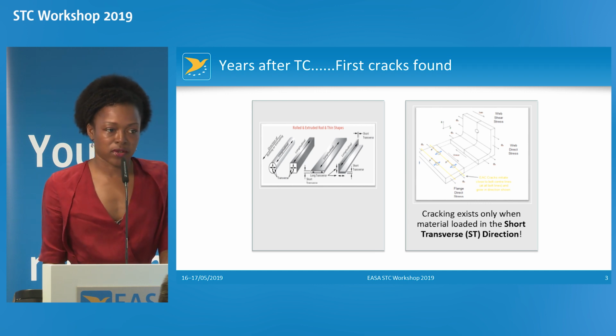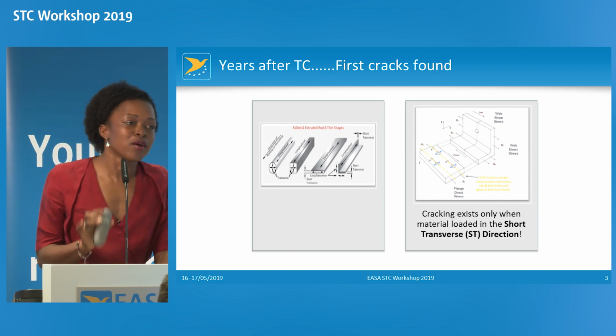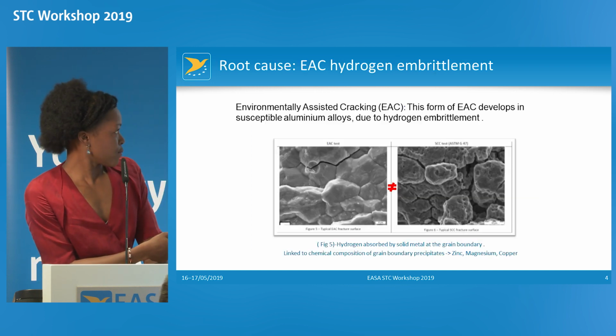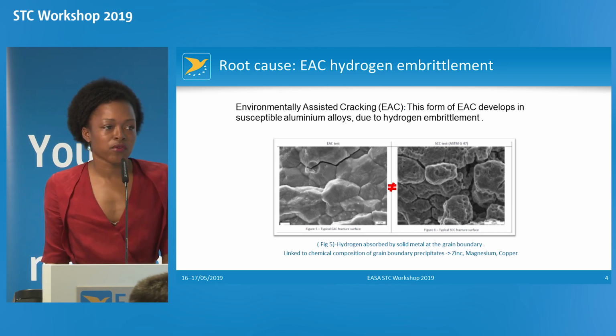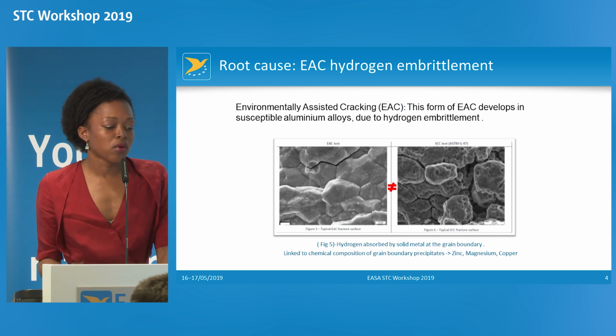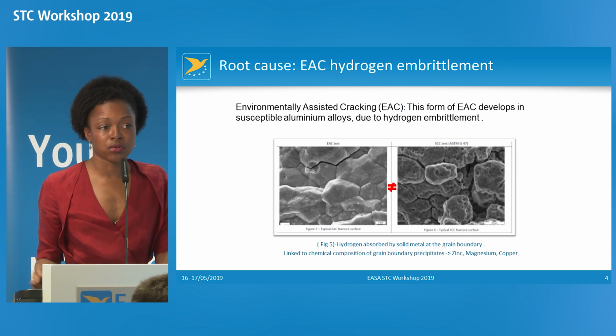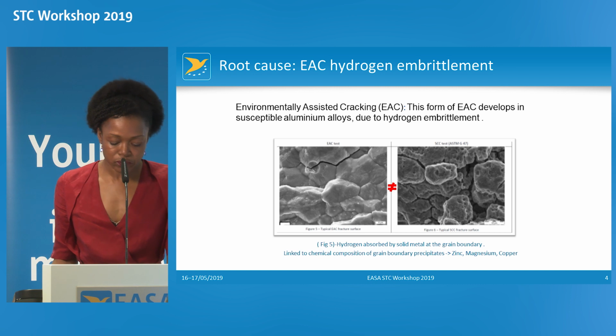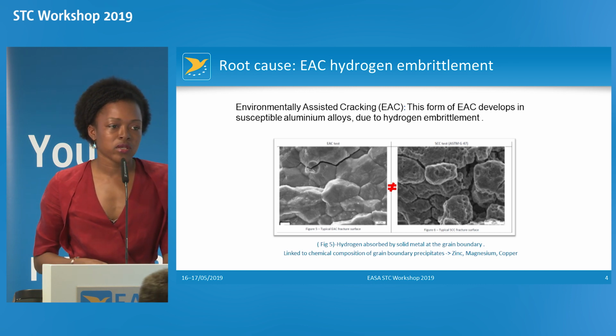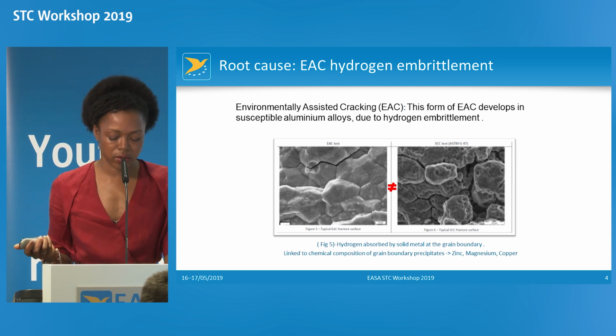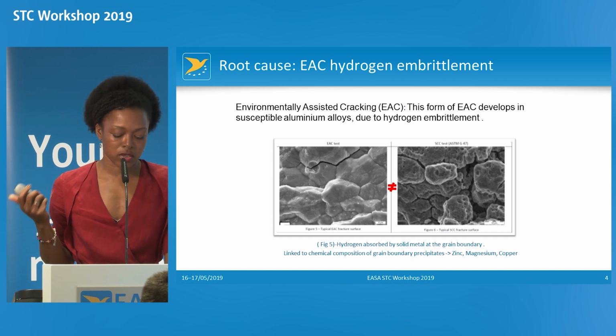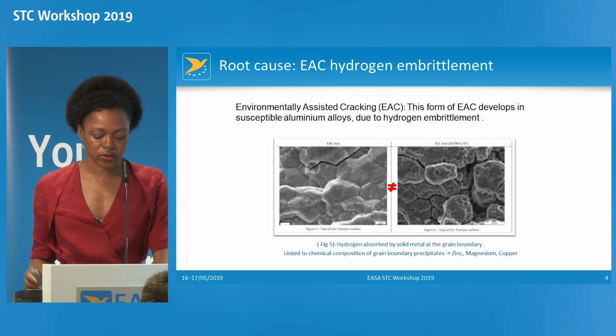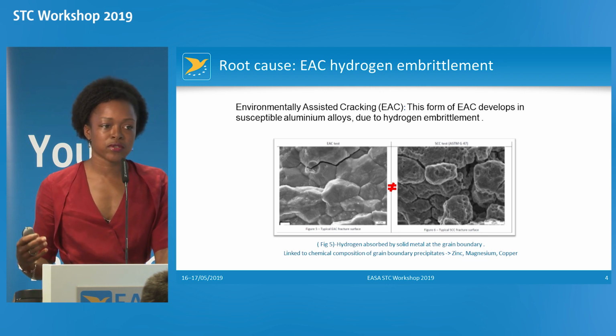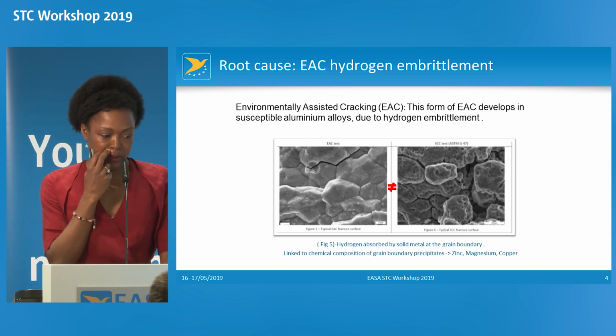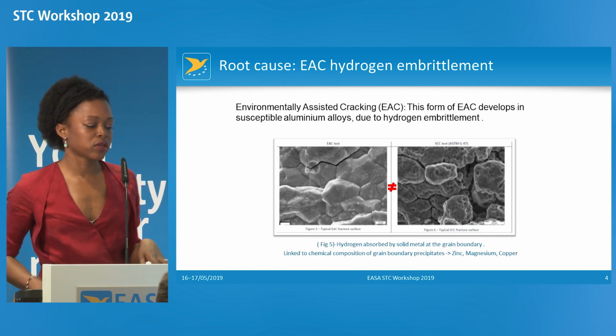Basically, it was identified that this issue was known, but not so well known. This issue is a form of environmentally assisted cracking, and this form of cracking develops on susceptible materials, the new materials that were developed, due to hydrogen embrittlement. Environmentally assisted cracking is a general terminology covering several phenomena, but this form appears when you have the susceptible material. It is due to hydrogen embrittlement, and it happens in normal operating environmental conditions under sustained stress induced by manufacturing.